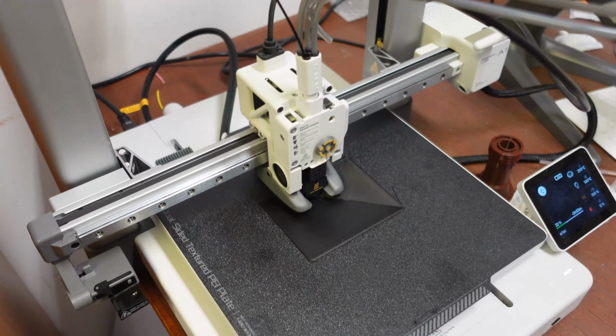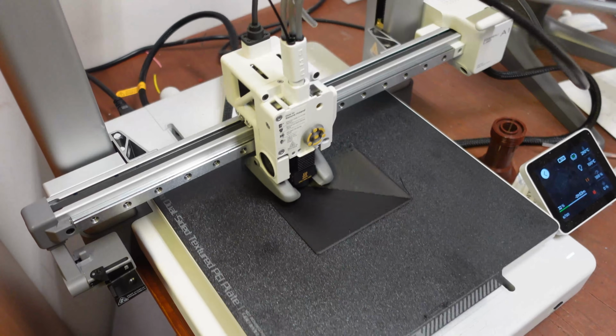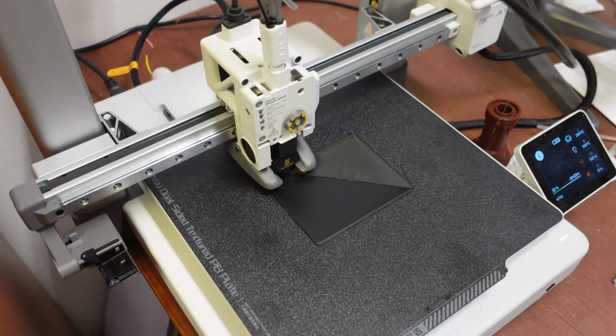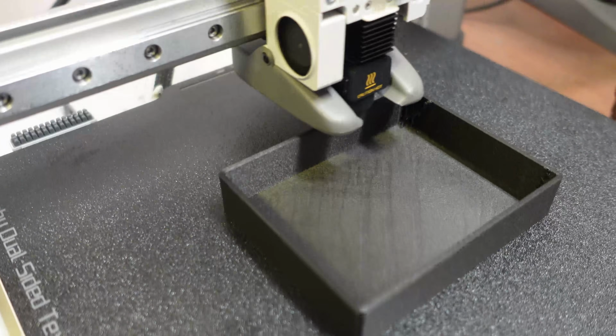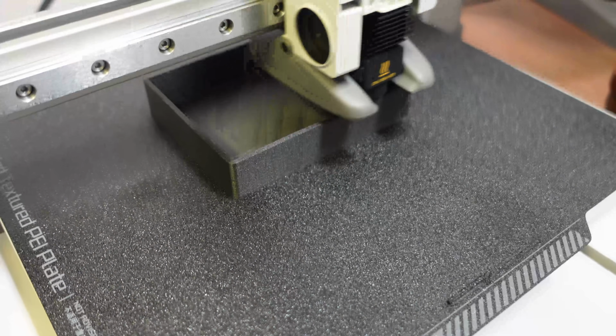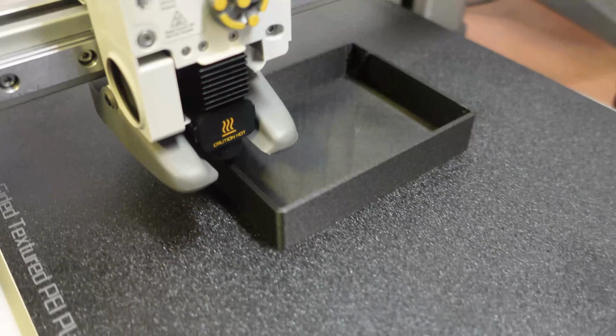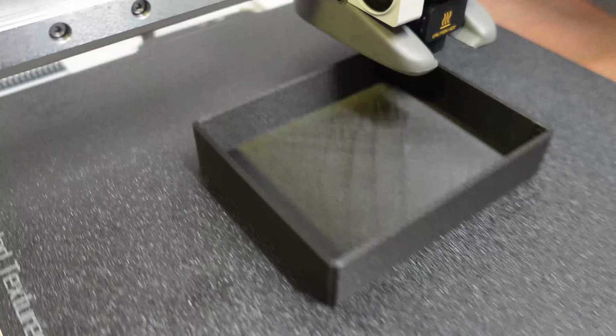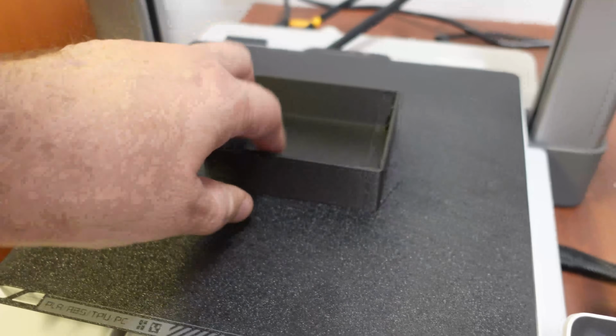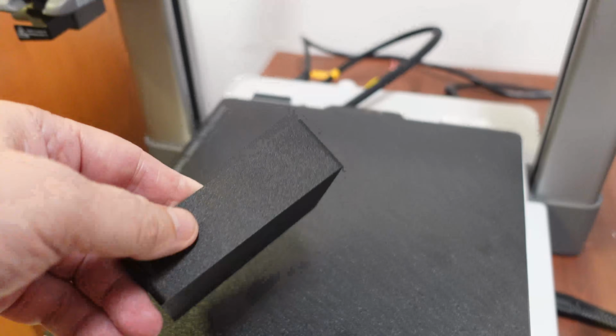I'm printing a small storage box. If there is any warping or cracking, it should be visible on this one. 20 more minutes of printing. It's completely okay, and even the side surface looks nice. Bed adhesion is good during the printing, and when it cools down it is removable.